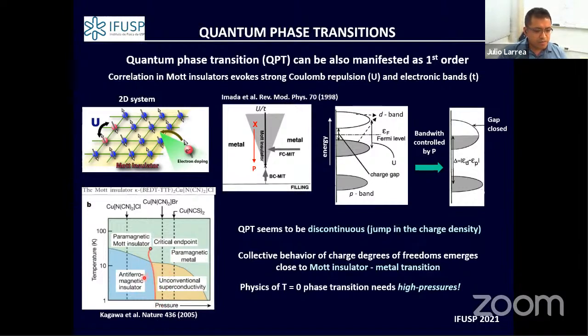There is a jump between the charge carrier density from the Mott insulator to the metal state. For this type of system, to achieve the quantum phase transition, you need the application of high pressure, another non-thermal control parameter.